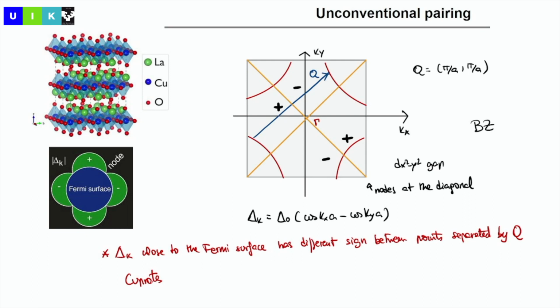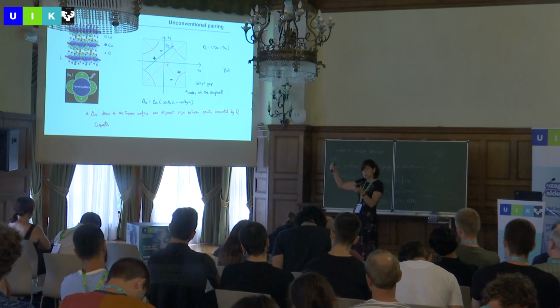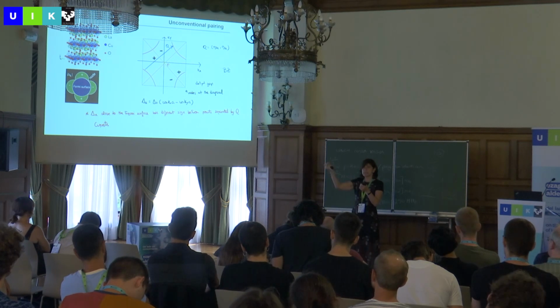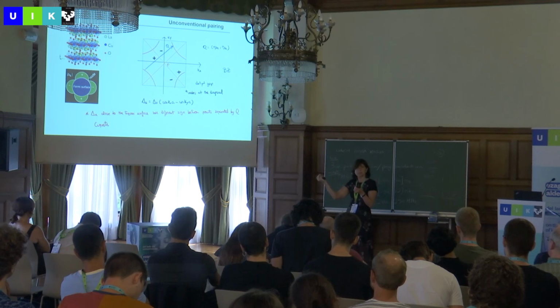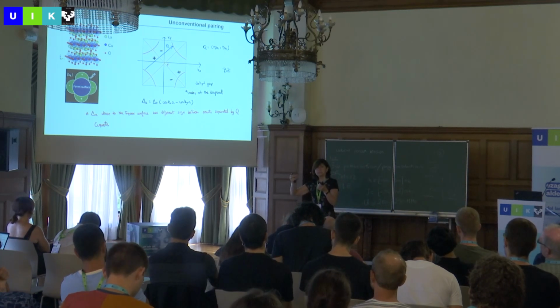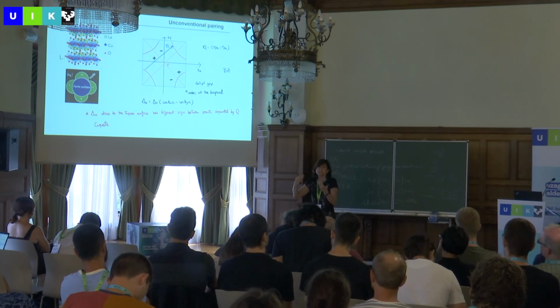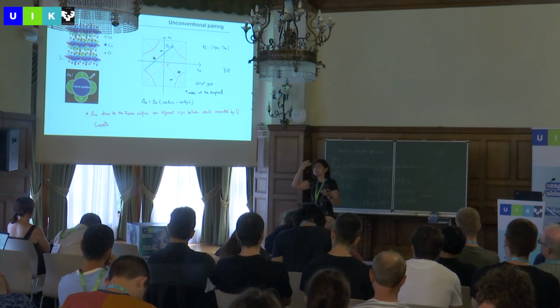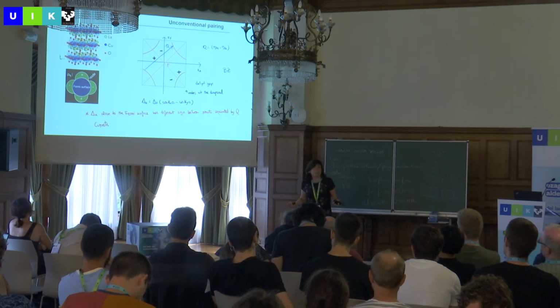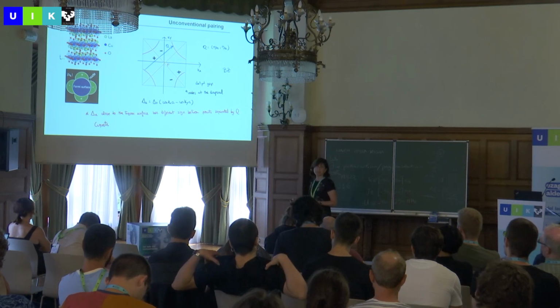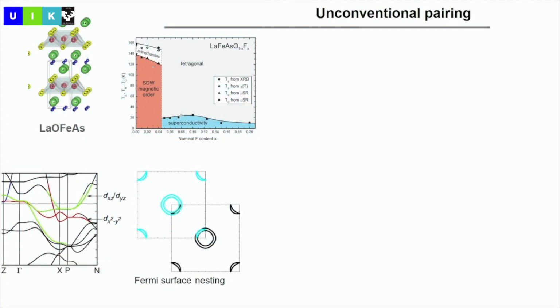So if you have perfect nesting at half filling, for instance, in the cuprates, but it's also the case that I was showing to you, then you have a strong instability because it costs the electrons no energy to do this scattering from one side to the other side of the Fermi surface. So it means that you are going to expect some kind of instabilities. One instability is that the system orders, and this you can explain as antiferromagnetic order, if your nesting vector is of this type. But you can also have superconductivity when you dope a little bit, which is what is shown here. So for the iron-based superconductors, you also have this perfect nesting. The nesting is, though, between the hole pockets around the gamma point and the electron pockets around the X point. And this is, in fact, why you can explain that the system has a spin density wave, in order to circumvent this instability of a perfect nesting.